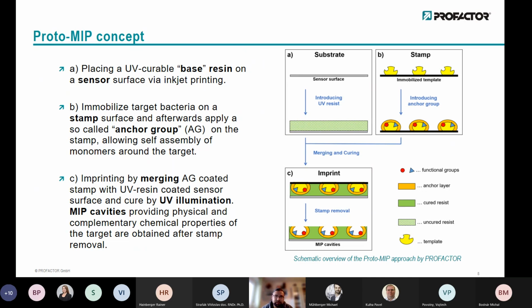So what we do here is, on the one hand, coat a sensor surface, can be a QCM, whatever layer, plastic layer, glass layer, an SPR substrate layer, with a UV resin that acts kind of as the base, and prepare a stamp with immobilized template and coat it with what we call an anchor group. This anchor group fulfills the role to introduce the functional groups that can self-assemble around the template and can be incorporated into the resin. On merging and curing, and initiating the curing, the anchor groups are immobilized in the resin. The resin is cured and hardened, so it's trapped inside, and releasing the stamp, the cavity is left behind with the functional groups there.